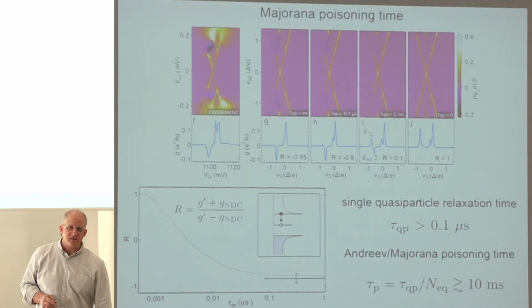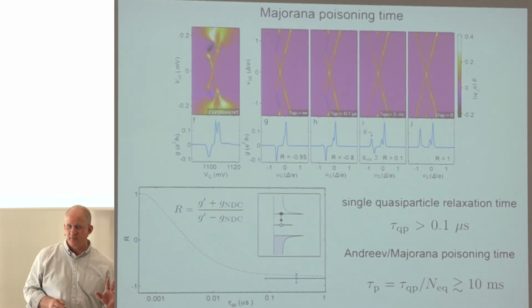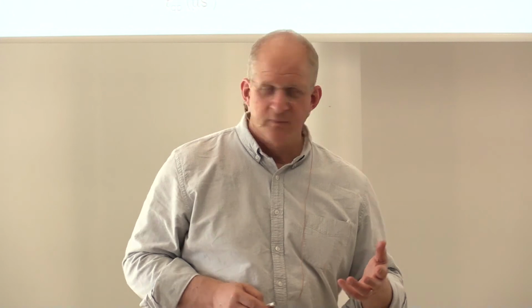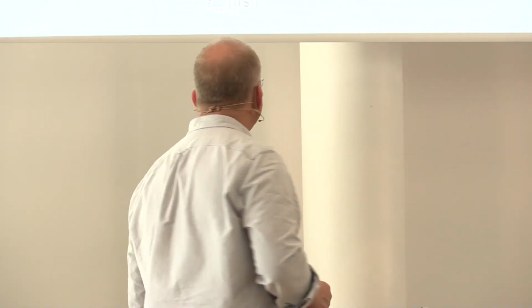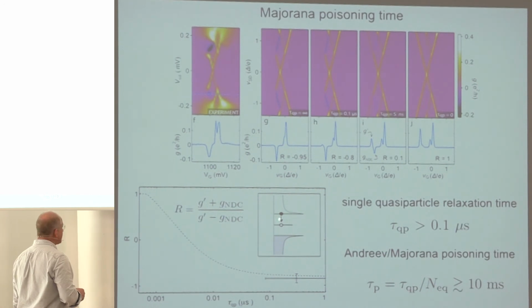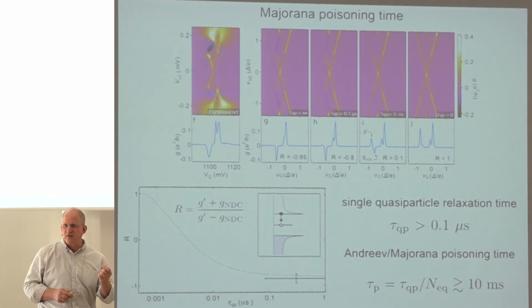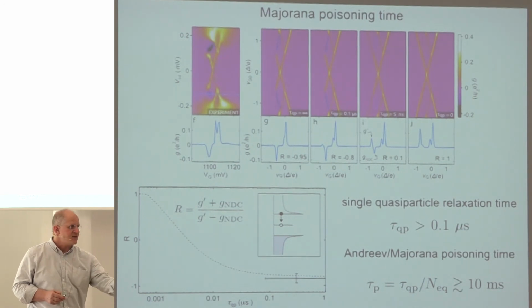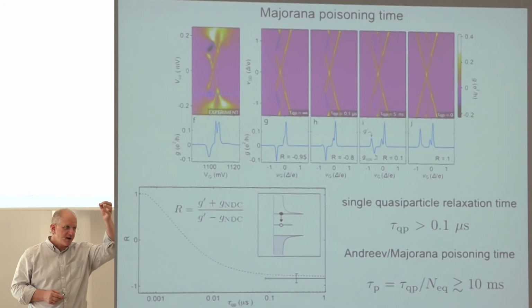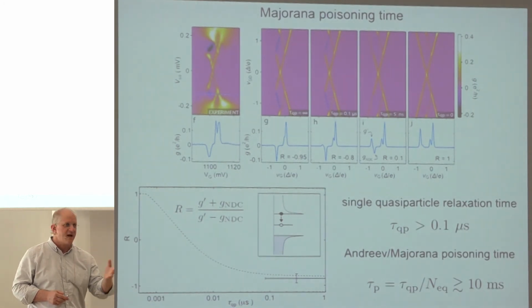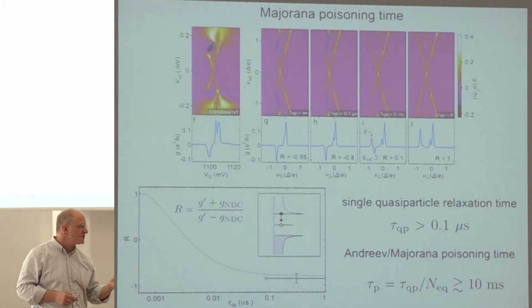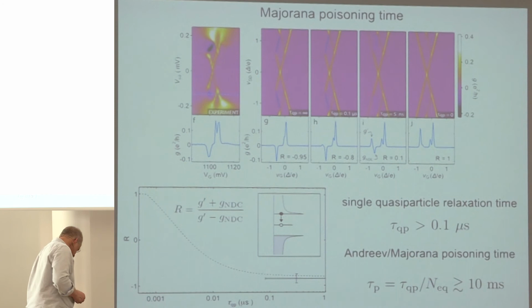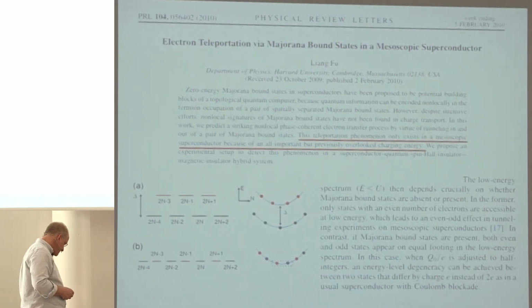Now that looks like a lot of analysis, so let me just summarize what the main point of that is. That's a really long time. If you compare that characteristic time to the characteristic time of the loss of coherence of a conventional qubit, 10 milliseconds is a real blessing. That says that you have 10 milliseconds before the very superconductor that's responsible for inducing proximity effect in this system pollutes the state, the Andreev state or the Majorana state, by dropping a quasiparticle, a free remaining quasiparticle, down into that state. You've got about 10 milliseconds on average before that time passes. And that says, we think, plenty of time to do the operations.